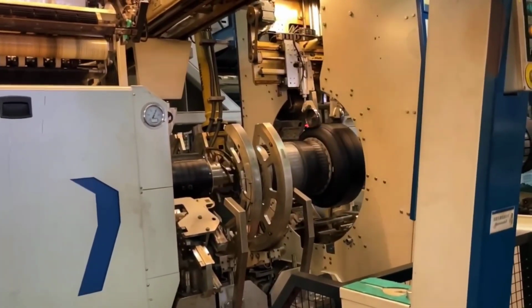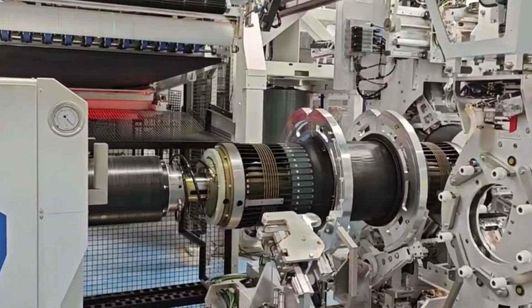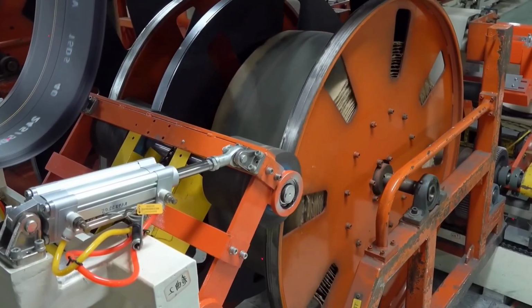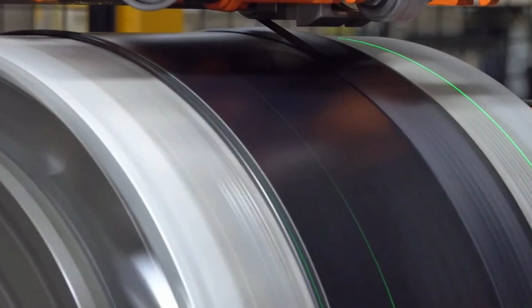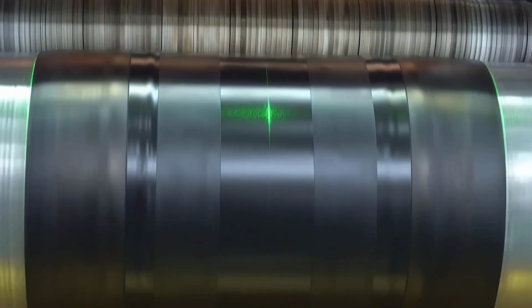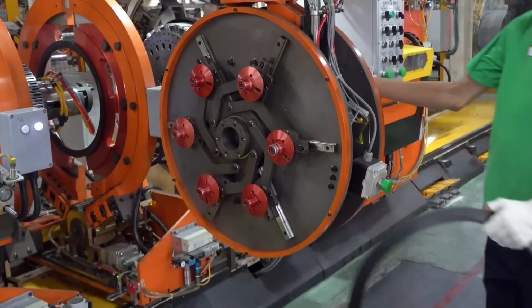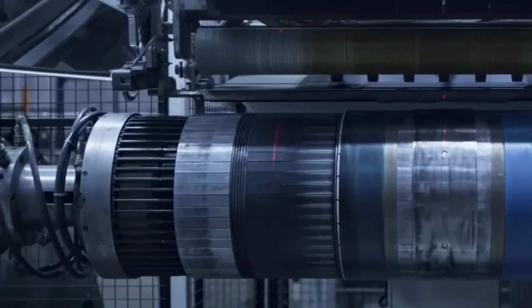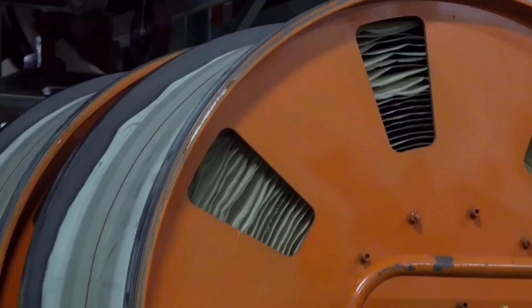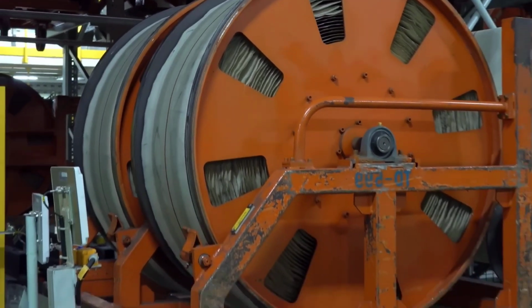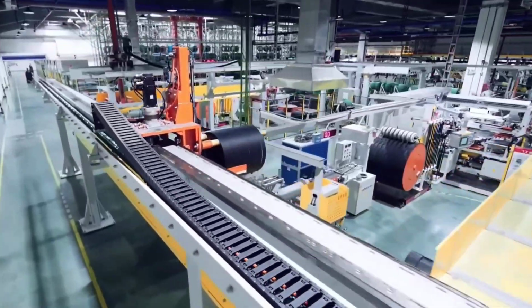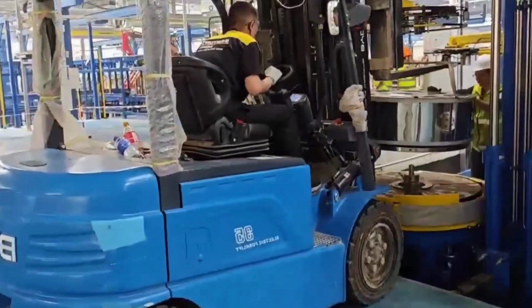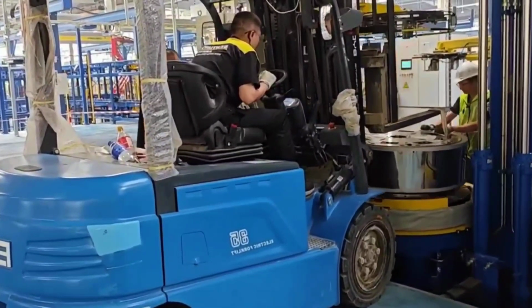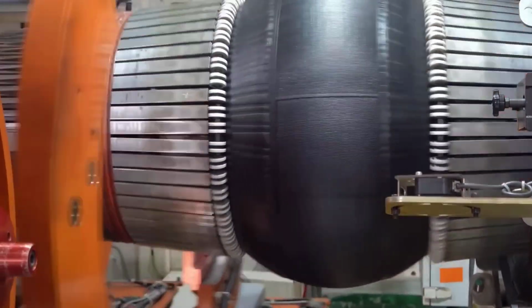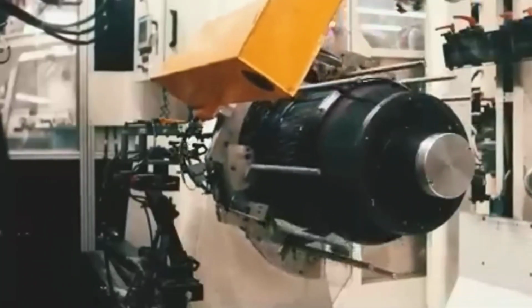With the capacity to assemble dozens of tires per hour, the entire setup must maintain tolerances within 0.1 millimeters, a near-perfect standard in the rubber manufacturing industry. Each rubber layer is applied to the drum by a servo-driven system, pressed tightly and aligned perfectly with the previous layers. To prevent overlap, misalignment, or wrinkling, force sensors work in tandem with industrial cameras to monitor every millimeter of the surface. Image and pressure data are processed in real time, allowing the system to instantly adjust the rotation, pressing force, and wrapping speed at each contact point.